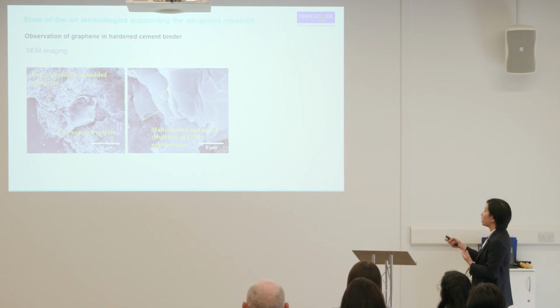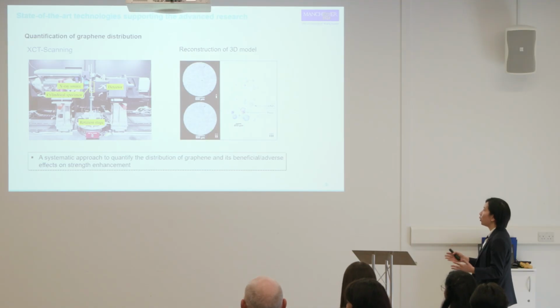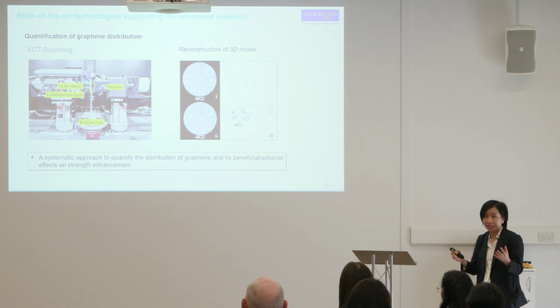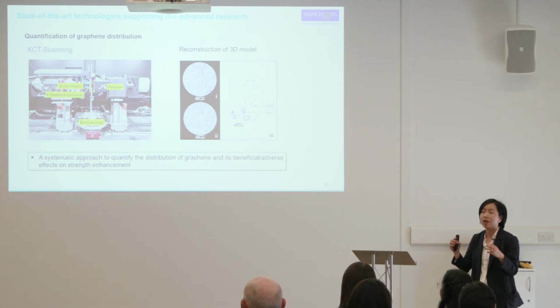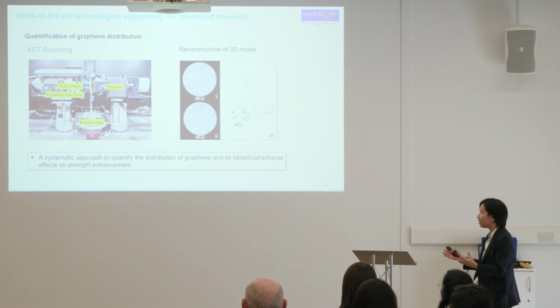In addition to conventional SEM observation to get a 2D image of graphene in the hardened cement, we also try to develop a more systematic approach to quantify the distribution of graphene. We use XCT scanning with thousands of XCT images. We were able to generate 3D models to get the graphene distribution in the hardened cement. With that, we can comprehensively establish the relationship between graphene agglomeration and strength development.